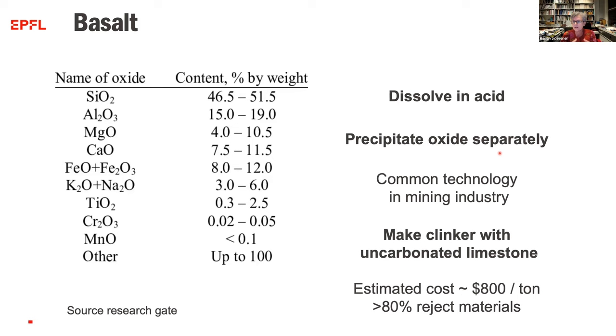And then you can make clinker from the uncarbonated limestone. There's just one problem. Well, there's two problems with this. The first is the cost. So the cost would be around $800 a ton. This is about 20 times higher than the cost of producing clinker today. And remember, even clinker with carbon capture and storage was only 3 to 4 times the cost.